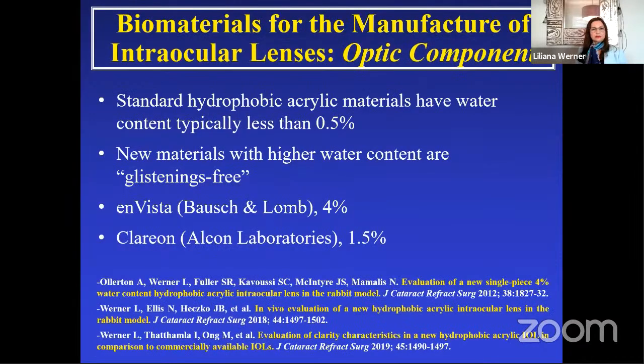I would like to remind you that standard hydrophobic acrylic lenses usually have a water content that's less than 0.5%. There are new hydrophobic acrylic lenses in the market with higher water contents, such as the enVista with approximately 4% and the Clareon with approximately 1.5%, and laboratory and clinical studies demonstrated that these lenses are glistenings-free and also do not show subsurface nanoglistenings.